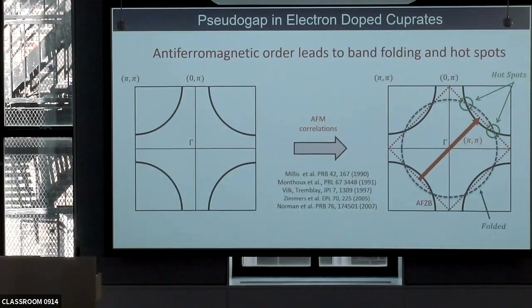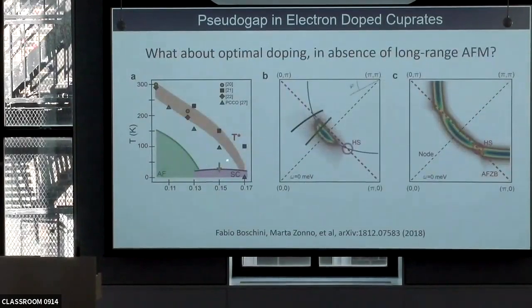And the question we'd like to ask is, what happens to the system when antiferromagnetism is not so robust anymore? So what Fabio has done is take a sample that was basically optimally doped, away from the very robust antiferromagnetism, and look at the Fermi surface. This is a simulation done here. Look in particular here and see, can we still see signs of a pseudogap? Can we track it in temperature? And can we relate this to the magnetic correlation length? So these are the data.